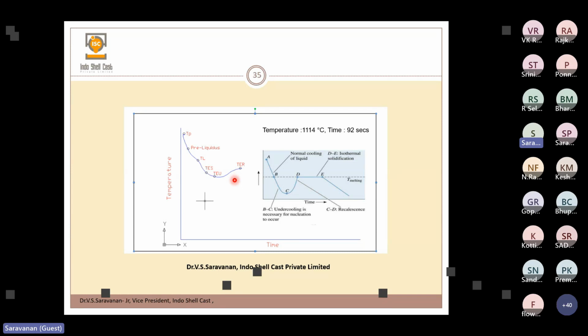And then how to improve the nucleation potential? Based on this recalescence, we can adjust the inoculation quantity, because many foundries add a constant percentage of inoculant, maybe 0.3% or 0.2% for gray iron and 0.4% for ductile iron. Invariably it is almost constant for all cases. But with active use of thermal analysis, we can adjust the inoculation a little bit. If the metal already has a very good nucleation potential, sometimes there is no need to add more inoculation, so we can reduce the inoculation percentage.